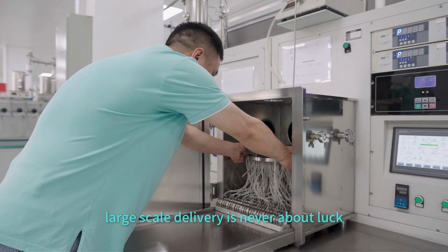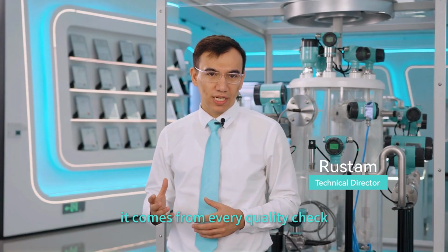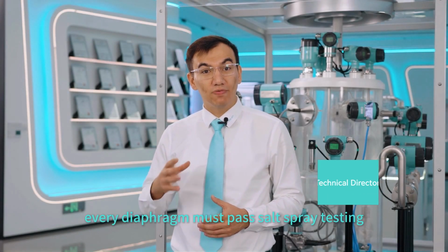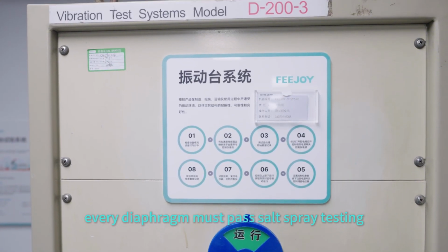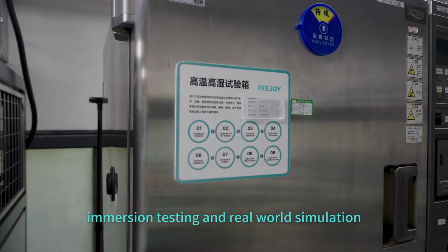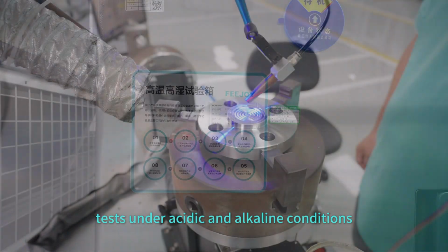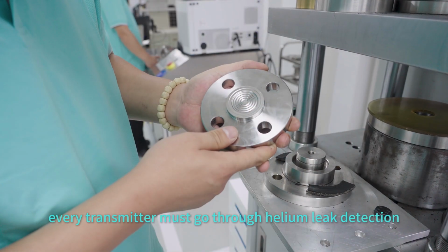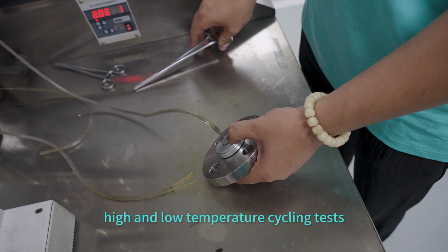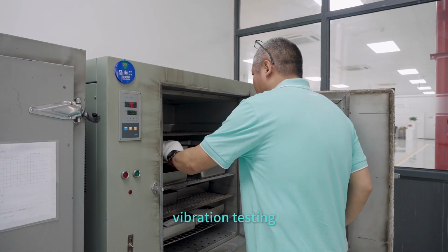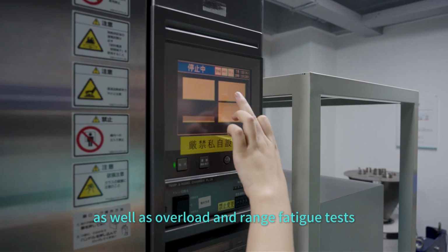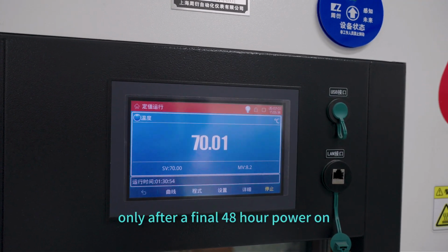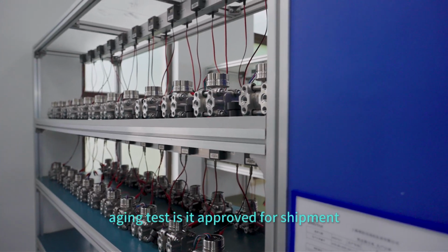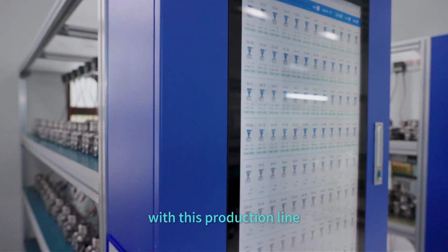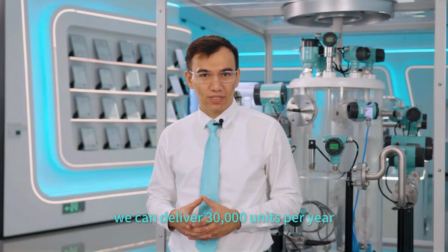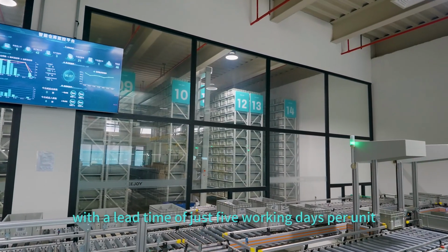Large-scale delivery is never about luck. It comes from every quality check before the product leaves the factory. Every diaphragm must pass salt spray testing, immersion testing, and real-world simulation tests under acidic and alkaline conditions. Every transmitter must go through helium leak detection, high and low temperature cycling tests, vibration testing, as well as overload and range fatigue tests. Only after a final 48-hour power on aging test is it approved for shipment. With this production line, we can deliver 30,000 units per year with a lead time of just 5 working days per unit.